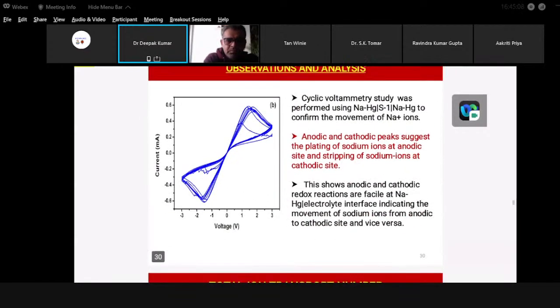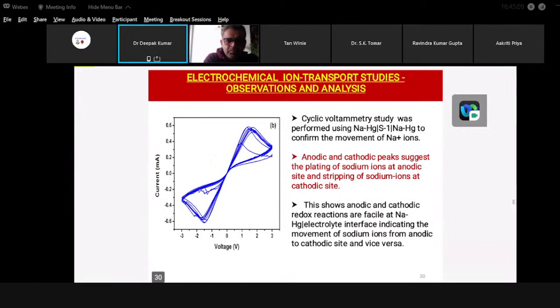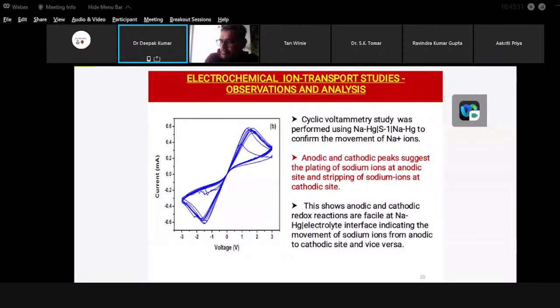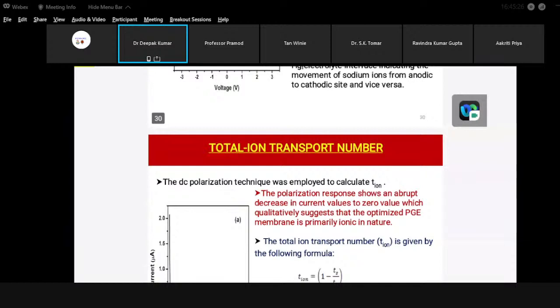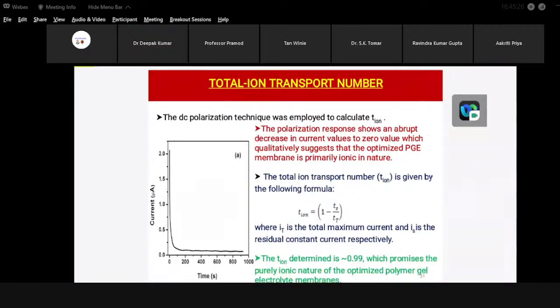If we have a look at the cyclic voltammetry with the reversible electrodes, anodic and cathodic peaks are seen, which is indicating the plating and the stripping of the sodium ions at the respective electrodes. The total ion transport number has also been measured, and it is found to be 99%, and this is indicating that the materials are purely ionic conductors and will have good ionic conductivity.